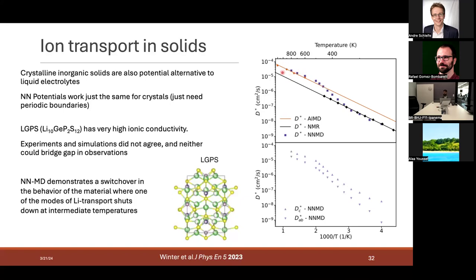So we train on data that looks like this red one, and we fit the machine learning potential. Then we do regular molecular dynamics like everybody else, but we're not moving forward quantum mechanical forces. We're moving forward machine learning forces. And we managed to go much lower in temperature. And we find out that we agree with both. At high temperature, the simulations were right. And at low temperature, obviously, the experiments were right.